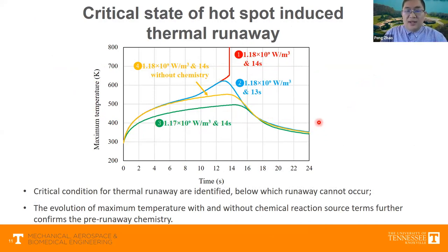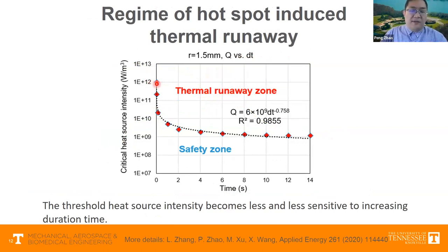So that means the threshold condition for hotspot-induced thermal runaway corresponds to a pair of critical heat source intensity and duration time. By identifying many different pairs of the critical conditions and connecting them, we now come up with a regime diagram for thermal runaway. So below this curve, it's rather safe. The hotspot cannot induce thermal runaway because of either low heat source intensity or short duration time. And beyond this regime boundary, we are having the risk of thermal runaway.